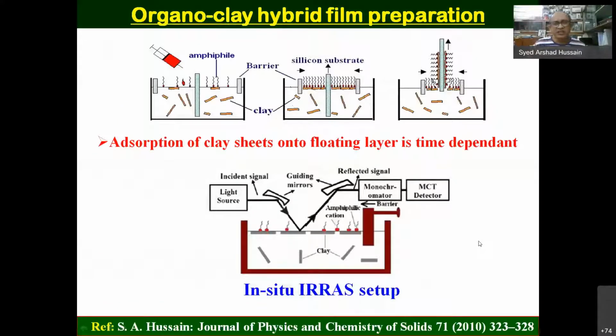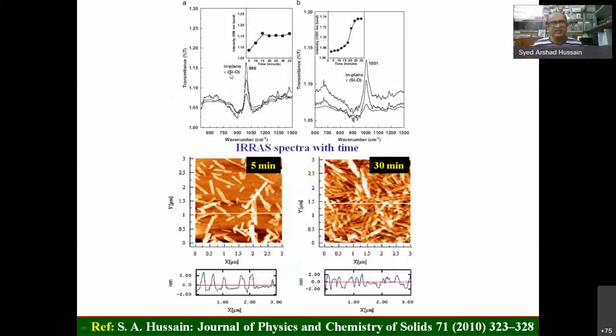Yeah. So during this, film formation is a time-dependent process. Say your clay is in the subphase, and on the surface is your organic material. So with time they come. You can monitor these things by infrared reflection absorption spectroscopy. You allow a light to fall on the surface, and if you measure the reflection with time, it will increase. So if you have a plot, you will see this is the silicon-oxygen vibration of the clay, and you see the intensity of the band increases initially with time, and after some time it flattens. That means all the clay systems have come to the surface.